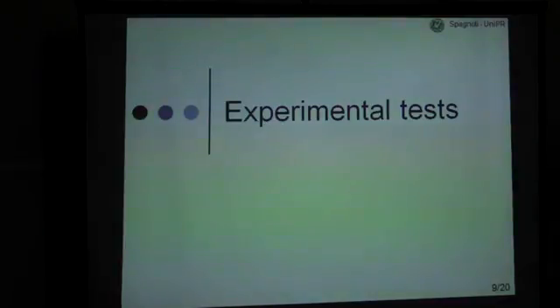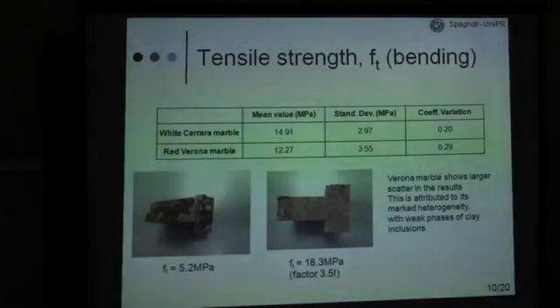So, as for the experimental tests, we first of all had, of course, the tensile strength from bending testing, and what I just want to mention here is the mean value of the strength, which is quite similar in the two marbles. But what you can see in the case of the red Verona marble is a much larger scatter of the results, with a coefficient of variation of about 0.3.